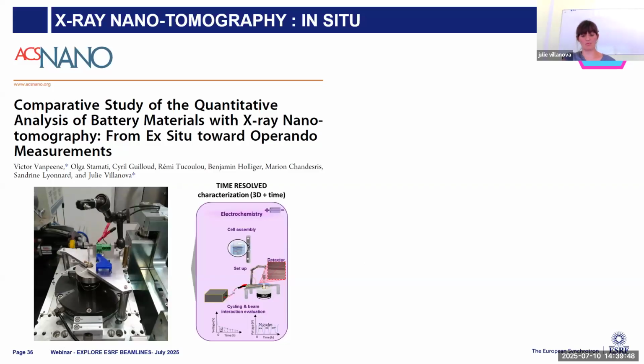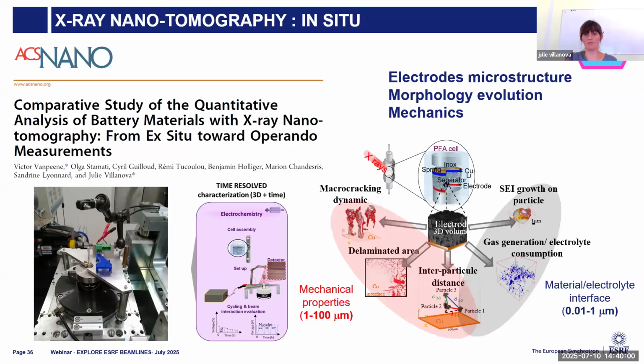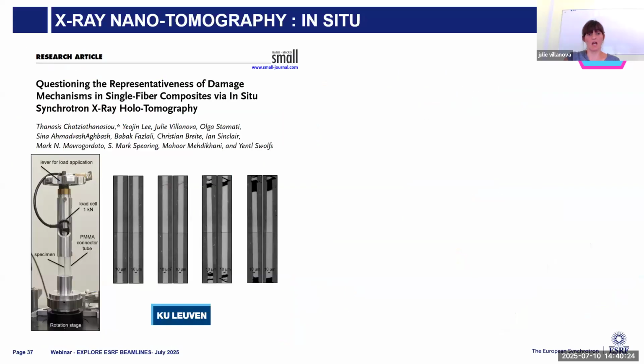The second setup we offer is the setup to perform in situ battery cycling, in order to look at the electrode and particle evolution, as for example electrode microstructure, morphological evolution, and mechanics. There are different studies that have already been performed at the beamline to look at macro cracking dynamics, delaminated area, interparticle distances, also gas generation, and SEI growth on particles. So those are the two setups we offer at the beamline, but we can also accommodate different in situ devices brought by the users. Here is an example of a tensile device that was brought to the beamline to look at the damage mechanism in single fiber composite.